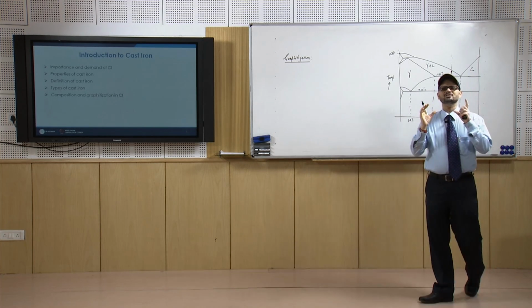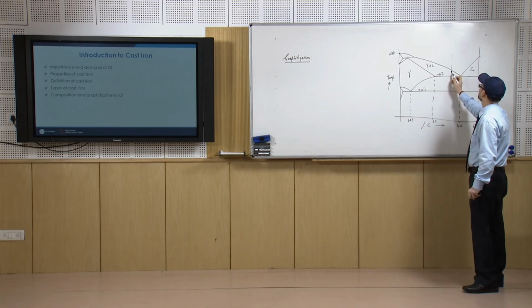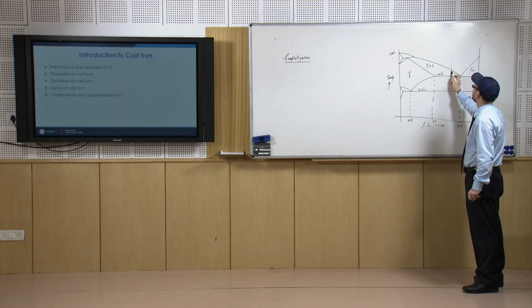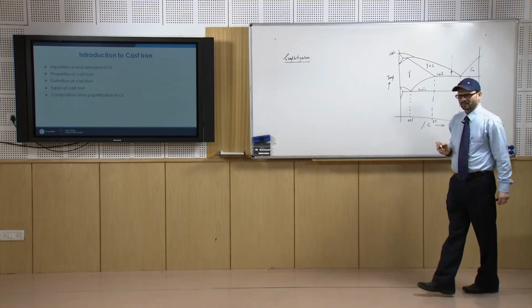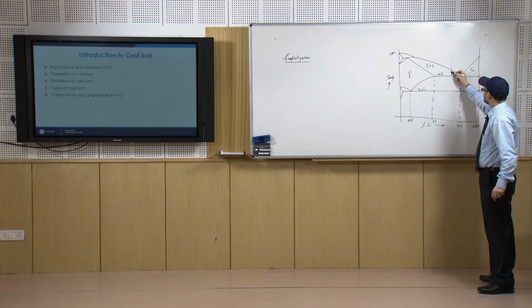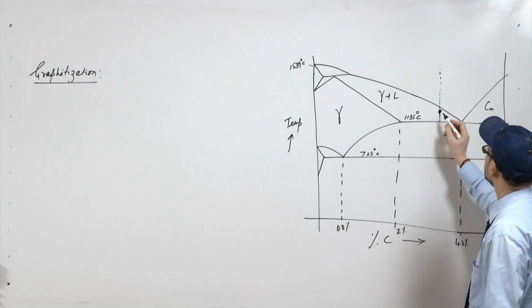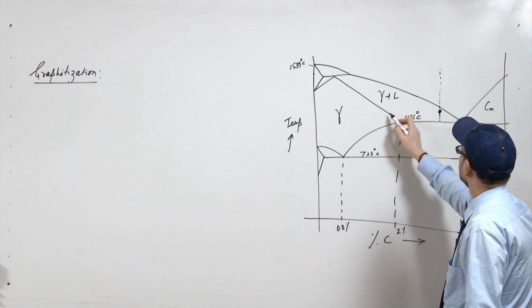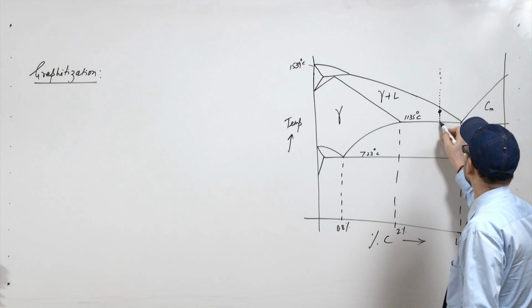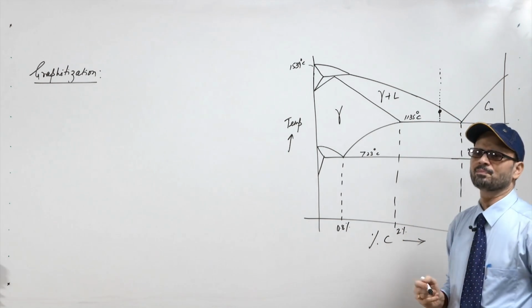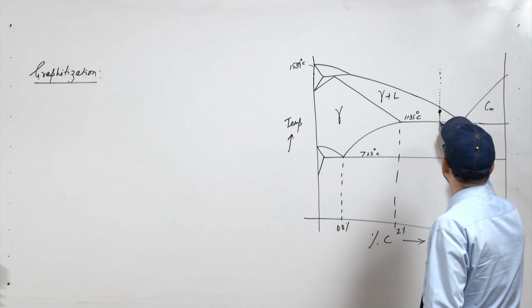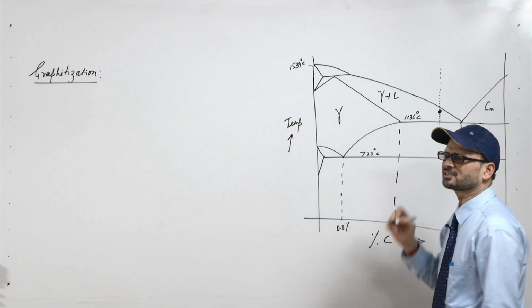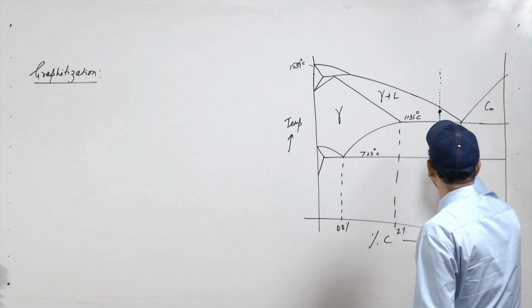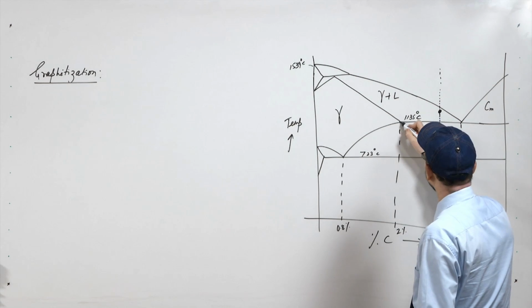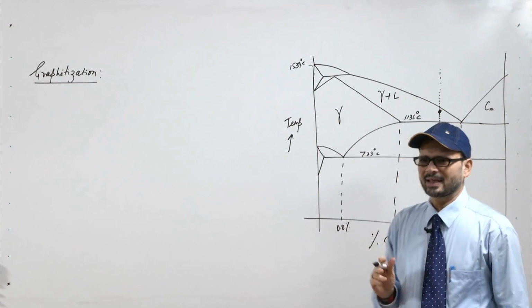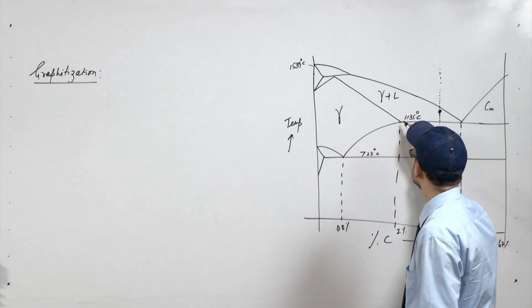Now, once you have come to a temperature below this, you have at this point austenite plus liquid. So, you have solid crystals of austenite coming out, and this austenite has a composition corresponding to this point. As the temperature comes down, this austenite will be losing the carbon. Up to this point, the austenite has a maximum of 2% of carbon. Once it comes just below this line, the freezing is completely complete, and you have austenite with a maximum composition of 2%, but once it comes down, again the carbon solubility in austenite decreases as per this line.